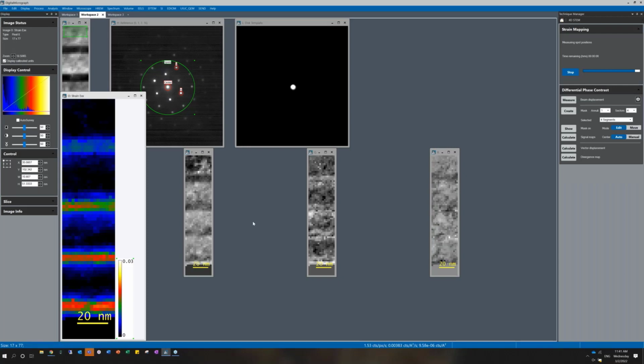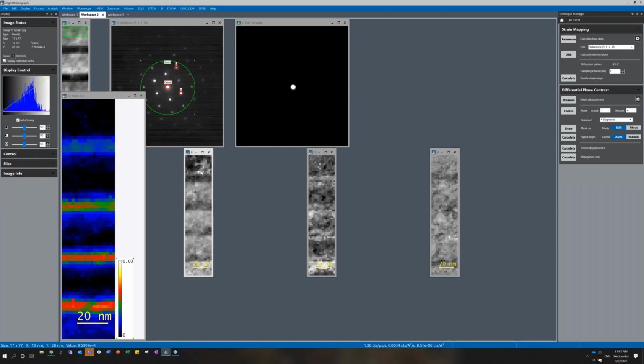The next map, this one is the strain in the Y direction. We don't expect to have much. You can see as I scroll down, if you look at the value shown here at the bottom left of the frame, it's less than 0.1%. So this is within the error margin. And if I look on here, it's 1.5%, 1.6%, and 1.72% here in the bottom part. Okay.